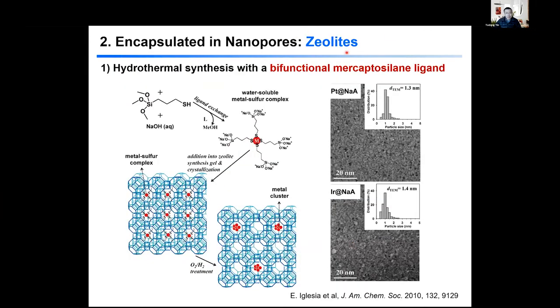Okay, and zeolite is another type, and people use basically coordination chemistry to prepare a silane complex with metal cations, and then they add that into zeolite synthesis. And after hydrothermal reaction, you end up with a framework of zeolite containing these complexes, and then you do oxidation reaction, get rid of the organic species, and induce the formation of oxide, for example, and then use hydrogen reduction to convert the metal species into metallic state, and you end up with these loaded or encapsulated nanoparticles.